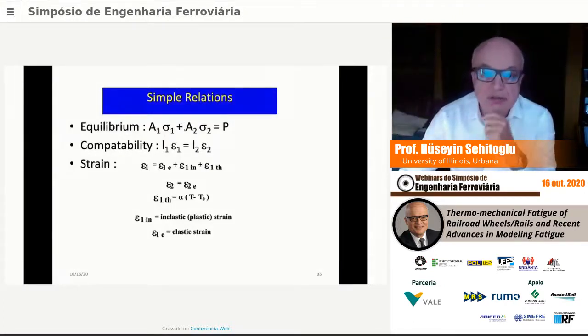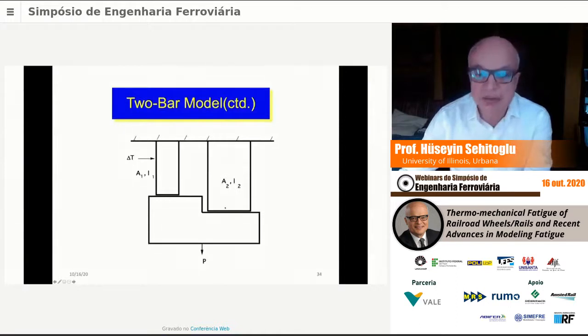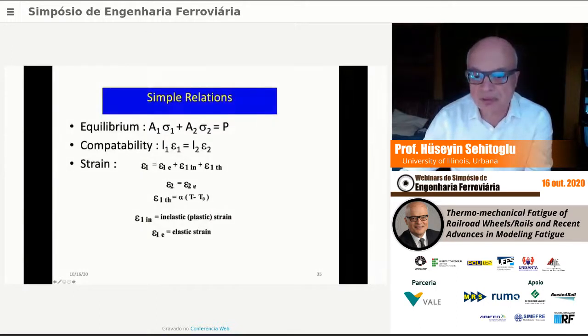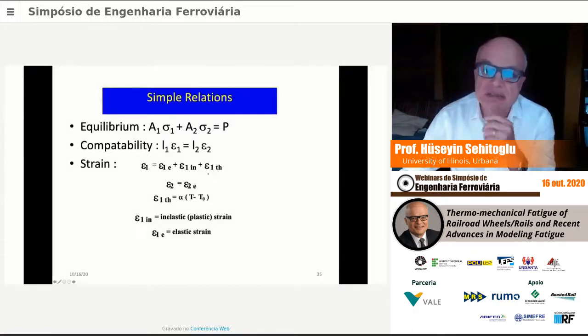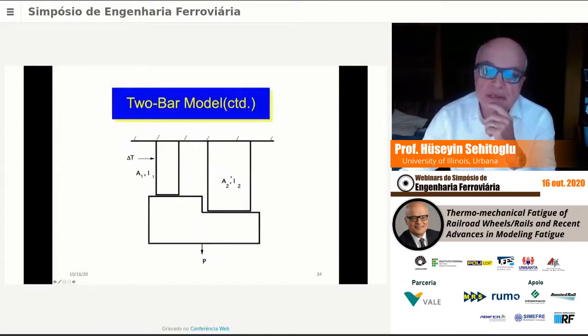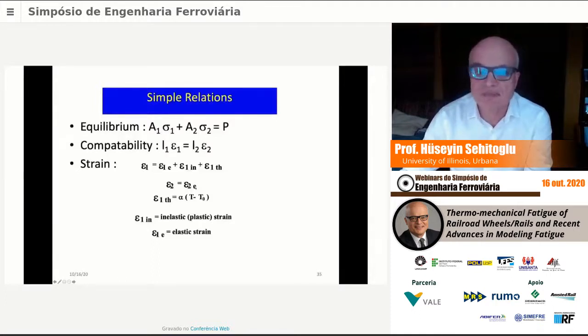That's an extreme case. If I write the simple equations, equilibrium: A1 sigma 1 plus A2 sigma 2 is equal to the net section load. Compatibility means L1 epsilon 1 equals L2 epsilon 2. The strain in bar one is elastic plus inelastic, inelastic meaning plastic, plus thermal, alpha delta T. But epsilon 2 is not being heated, and it's primarily elastic. That's what happens in a wheel. Epsilon 1 thermal is, of course, alpha times T minus T0. T0 is the starting reference temperature, T is the current temperature, and alpha is the coefficient of thermal expansion.